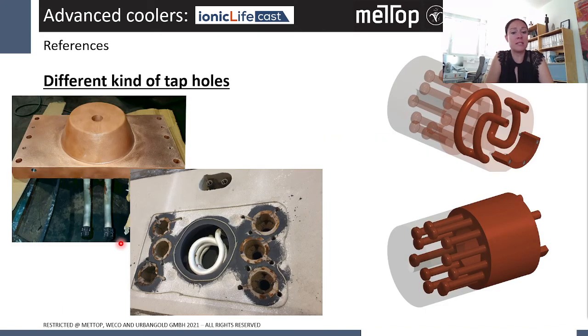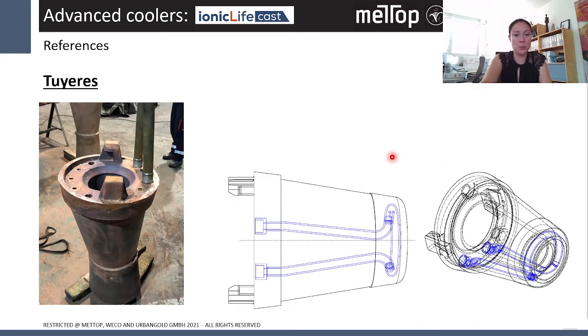Also, different kinds of tap holes can be realized with our casting technology. You can see here a normal tap hole. But on the right-hand side, you can see a specially designed tap hole, designed by Metop for a ferro alloy furnace, where you also have the cooling loops inside with these copper fingers. So you have a cooled area also at the very front. This is a very nice cooling product.